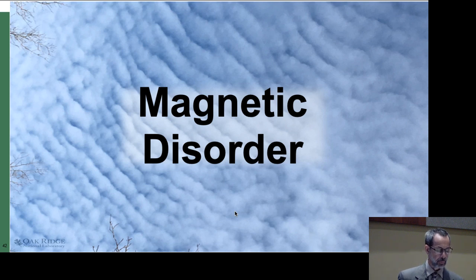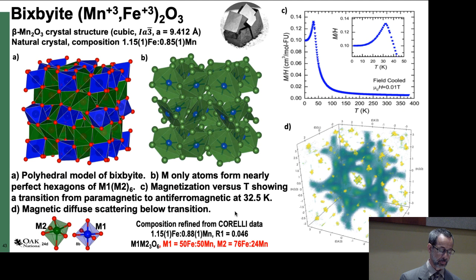The last example I'm going to show is a magnetic disorder. This is done at the spallation source with the CORELLI instrument. This is another mineral analog of what appears to be a disordered magnetic system that does not show long-range order at low temperature. The iron and manganese are distributed in these octahedral sites randomly on 2 different sites. You can again find the whole solid solution.